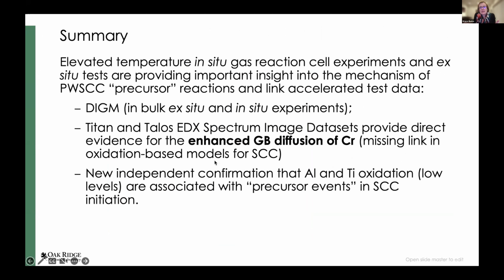So basically, what I want to get across to you is that you can do some very interesting bulk work and complement it with in situ using potentially non-conventional specimens, but it can give you independent confirmation of the diffusion-induced grain boundary migration in bulk and in situ. The Titan and the Talos STEM-EDX spectrum image data sets provided the information that we needed concerning diffusion of chromium, the significantly enhanced diffusion of chromium that had been a missing link for some oxidation-based models, and new independent confirmation that titanium and aluminum oxidation, even at those low levels, are associated with this precursor event.